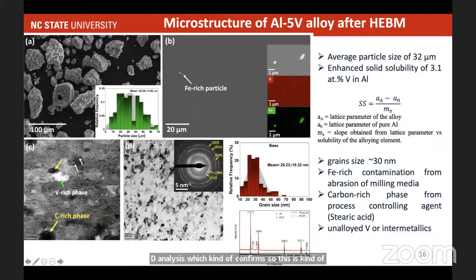This is the powder, and these are the same images for the powder. If you do SEM on this particular alloy, you have a few intermetallics present here and there, and some impurity like iron-rich intermetallic. Otherwise, the solute is uniformly distributed. We do TEM and see it's a really small length scale now, and we start having a pretty complex microstructure. Initially, we thought it was going to be all uniform, but we see vanadium solute-rich and solute-poor regions. We also used a process controlling agent which introduces carbon activities and carbon impurities. So the microstructure is pretty interesting. At micron scale, it looks pretty uniform. At nano scale, there are lots of heterogeneities.